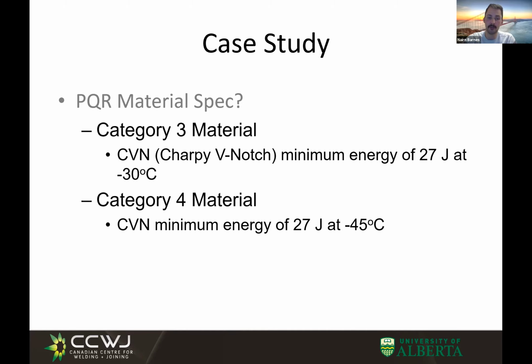So one of the things that we do within our company is we very often have requirements to go between Cat 3 and Cat 4. So where we're going, Cat 4 is actually an even more intense requirement. So it's minus 45 degrees C. So essentially what we do is we test our welds to category 4. So we test them at minus 45. And by passing minus 45, they made a recent change to the code that allows you to now be good at every temperature range above that to the rest of the categories, right? So essentially back up to ambient room temperature. So it's a really, really good change, because previously it was very annoying and you had to have a bunch of testing to qualify one procedure, or you had to have a bunch of different welding procedures, all good for different temperature ranges. Now, as long as you test in the most severe conditions, you can get the allowance for the other less severe conditions.